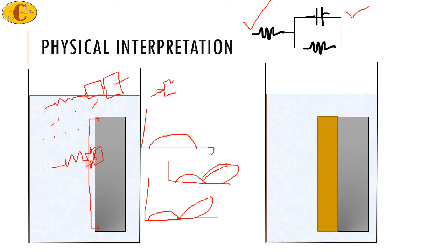If you consider the coating case, in the coating conditions, usually in initial stages, you do not see two semicircles at all. You'll only see a single arc or a straight line indicating that the coating is really good. So the solution resistance is followed by a single parallel arrangement, and anything over here indicates the high impedance for the coating. So if you have a straight line, usually you do not even have this resistance. You'll only have a resistance and a capacitance that will give you the fitting for this arc.